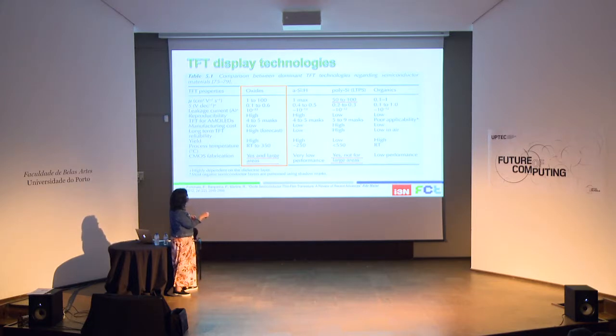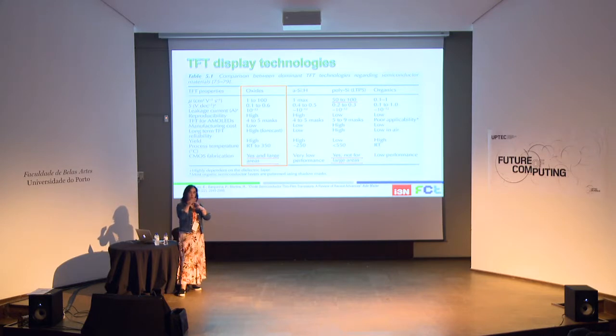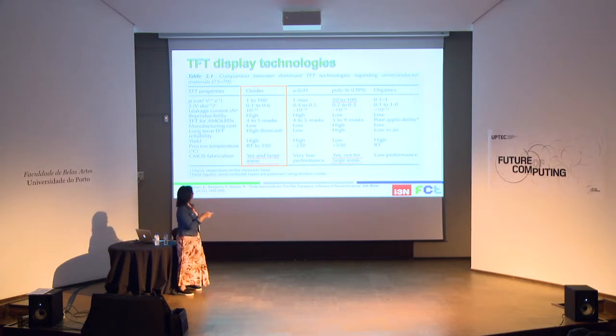we can see that for oxides, we can reach mobilities of the order of 100 square centimeters per volt per second. For example, amorphous silicon is limited to 1, because the material is amorphous, presents some defects. Polysilicon also, we can reach values of 100, but since it is not a homogeneous material, has different crystals. For example, if I'm looking for large televisions, large displays, I cannot have uniformity over a large area, so this is quite good, maybe, for mobile phones, where the display is not so big.